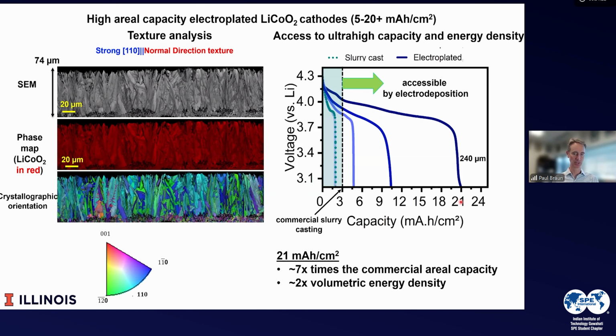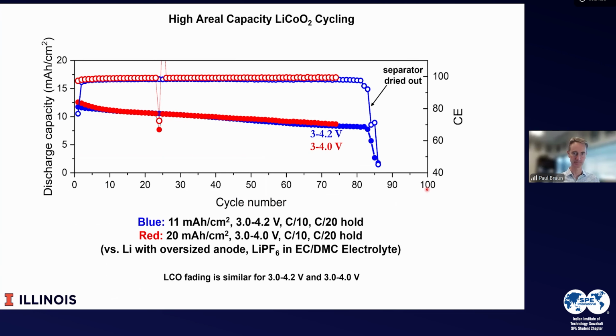So capacities of 10 or even 20 milliamp hour per square centimeter. That means the system has much higher areal capacity and much higher volumetric energy density than can be obtained in a commercial system. It cycles quite well even when thick. These are 10, 11, and 20 milliamp hour per square centimeter, and they've now cycled about 100 times. And actually what starts to fail is the separator, not the active material.